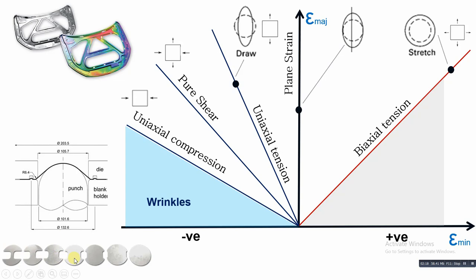In general, we call any point here a case of stretching, and any point here a case of drawing. So this is stretching and this is drawing, because here we have epsilon major and epsilon minor equals zero, but any point after this point, epsilon minor will have a positive value. So this is a case of stretching, and here epsilon minor has a negative value, so it's a case of drawing. So to conclude, a Nakajima test, for example, or we also have Erichsen, we also have Marciniak, all